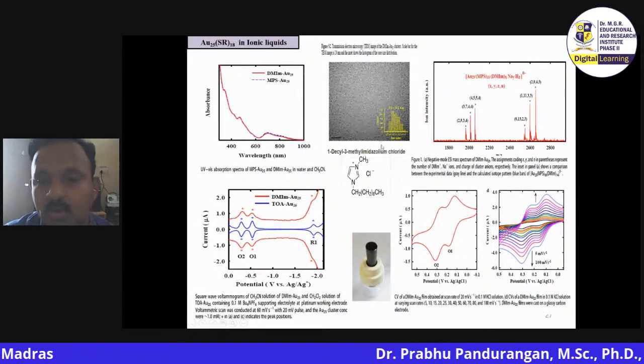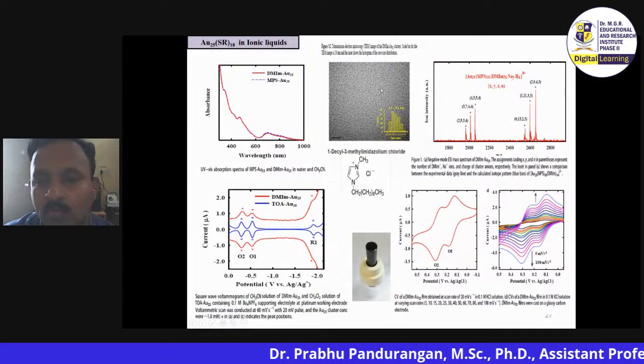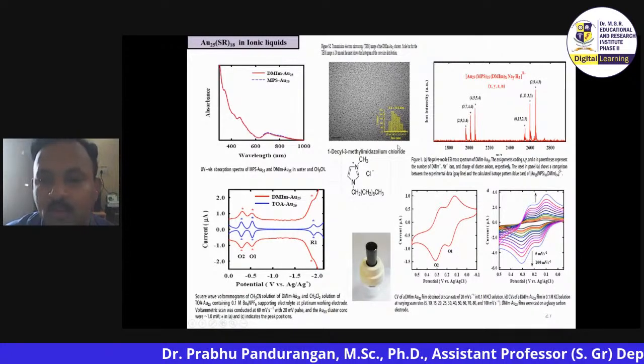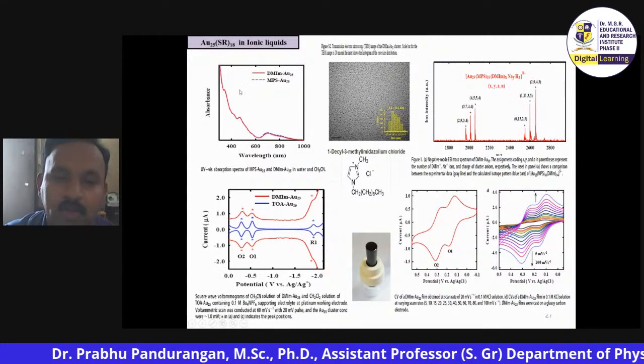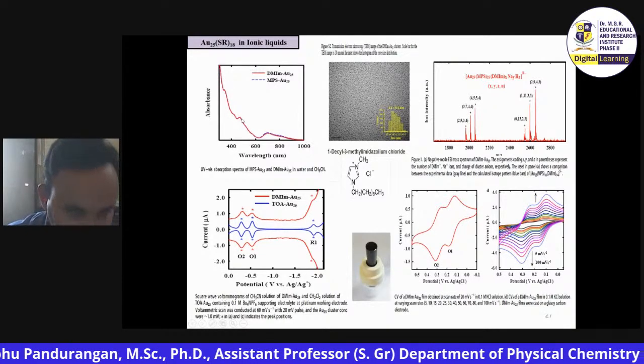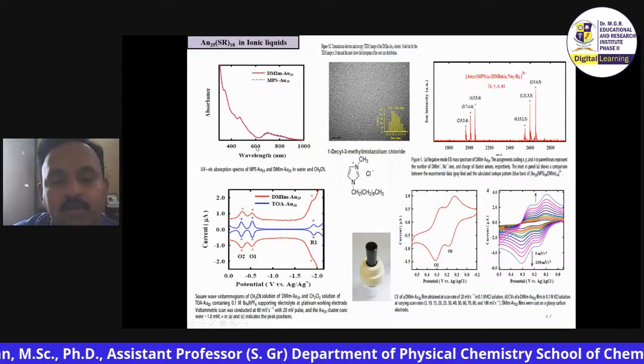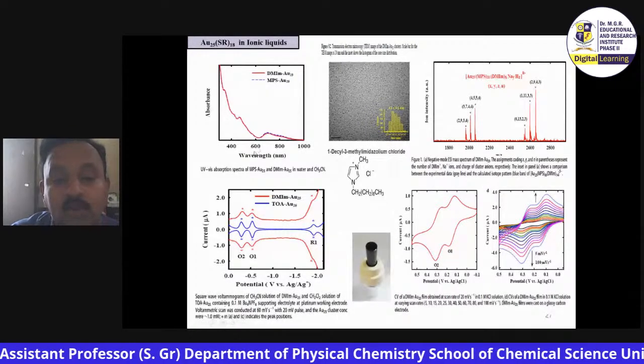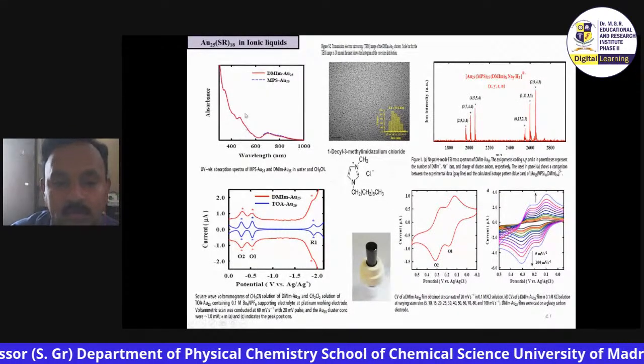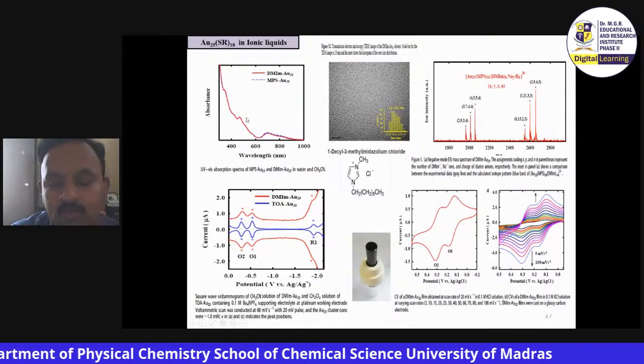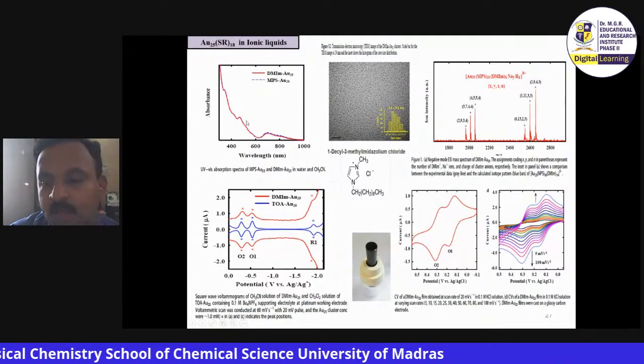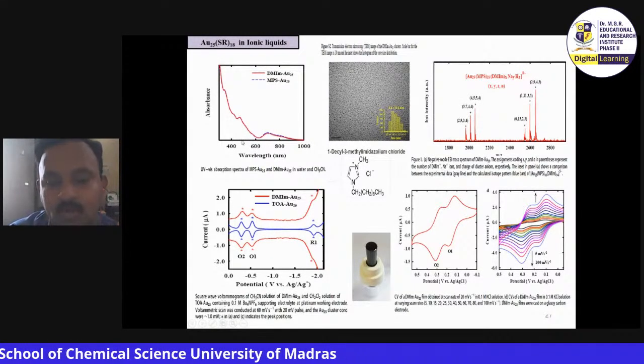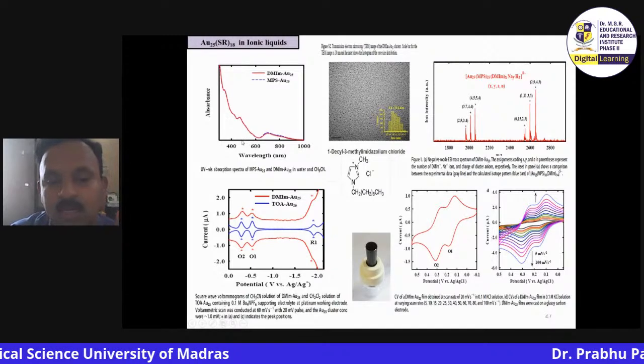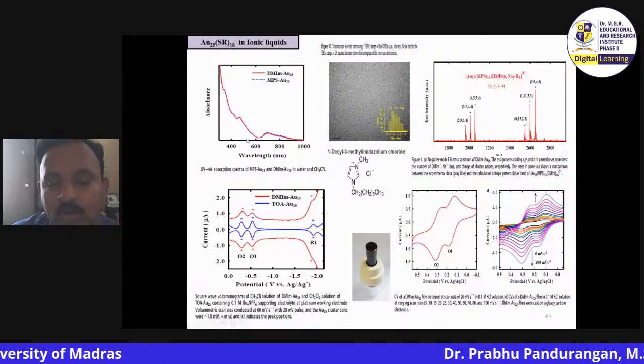But you can take this gold 25, you can see the TEM image of 1.1 nanometer, mostly close to 1.1 nanometer, and you can see the response of this UV. I said gold nanoparticle will give you a peak at 520 nanometer. I hope most of you would have seen metallic particles, but this paper talks to you about molecular gold particle, gold 25, with a 1.1 nanometer.